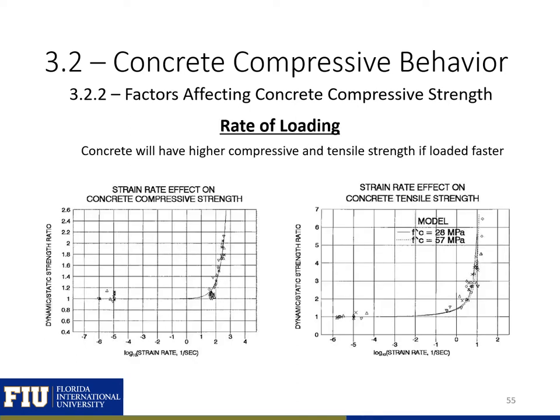Similar to steel, the rate of loading will impact the strength of concrete. The dynamic impact factors for compressive and tensile concrete strengths are shown in these two plots for differing strain rates. Concrete will have a higher observed strength under higher strain rates. Note that this highlights the importance of using the proper loading rate when running material tests on concrete. Applying the load too quickly on a concrete cylinder can make your concrete seem stronger than it actually is.